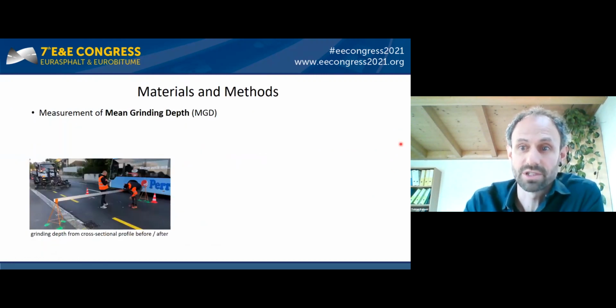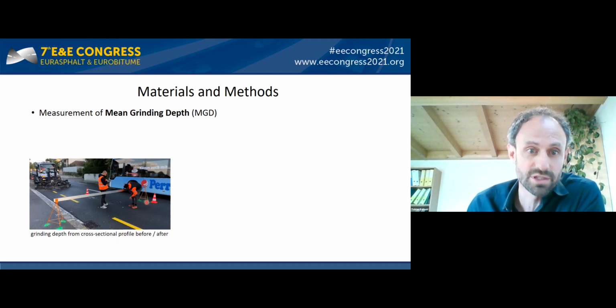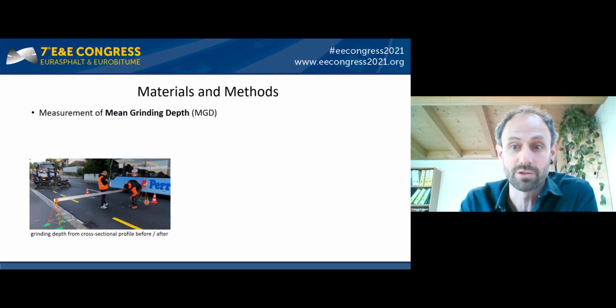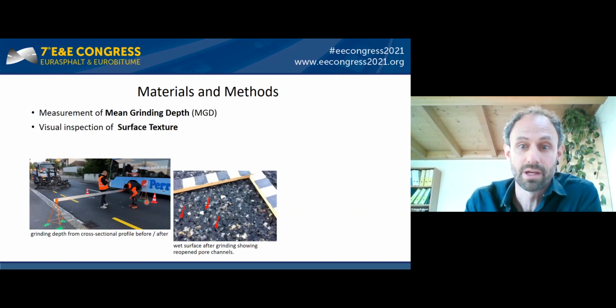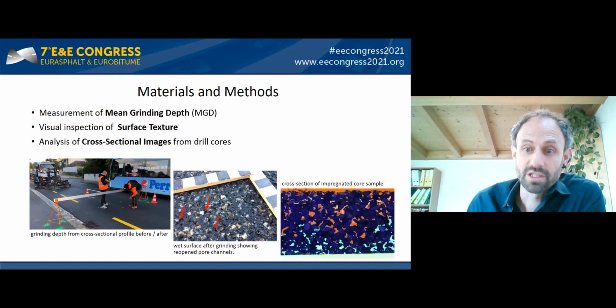Besides the CPX acoustic measurements after grinding, the main interest also lied in determining the actual grinding depth. With a simple method, we measured cross profiles across the street lane, and with difference before and after grinding, we calculate the mean grinding depth at resolution of about 1 millimeter. By visual inspection of the surface texture, we looked for signs of reopened pore.